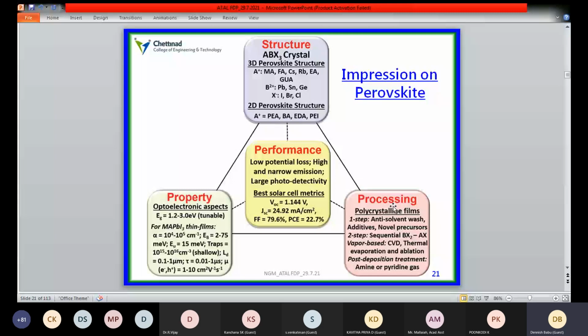So if we optimize these three parameters, structure, property, and processing, it is expected that this perovskite material will perform very well, with low potential loss, high and narrow emission, and large photodetectivity. It is expected that this perovskite material can produce an open circuit voltage of 1.14 volt, a short circuit current of 24.92, and a fill factor of 79, and it is theoretically predicted that they will be able to produce 22.7% power conversion efficiency.